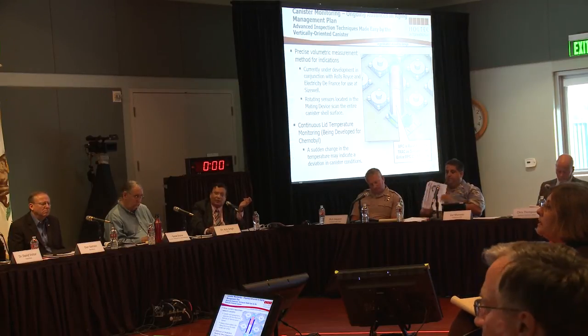You can see that the deposition on vertical surfaces is much, much smaller than on the horizontal top lid. In our case, the top lid is thick, so you don't much care if you have deposition at the top. You want to protect the cylindrical shell, and our system seems to be working very, very well in that respect.